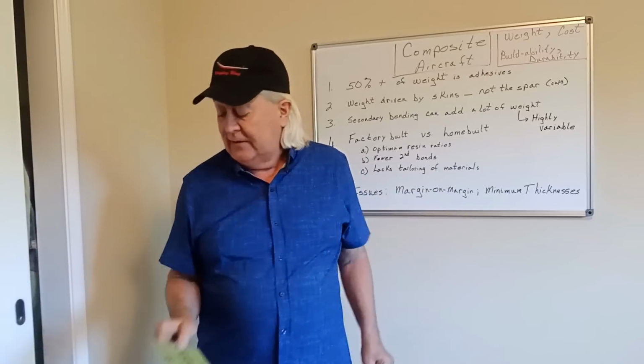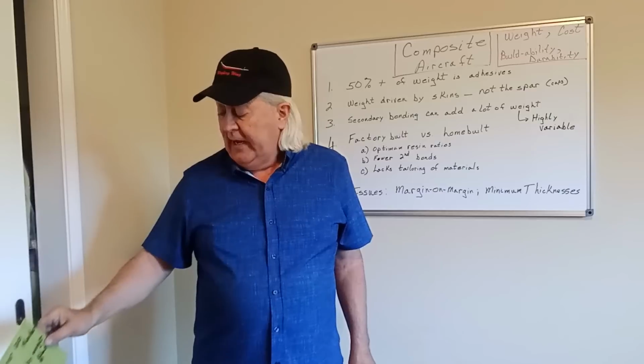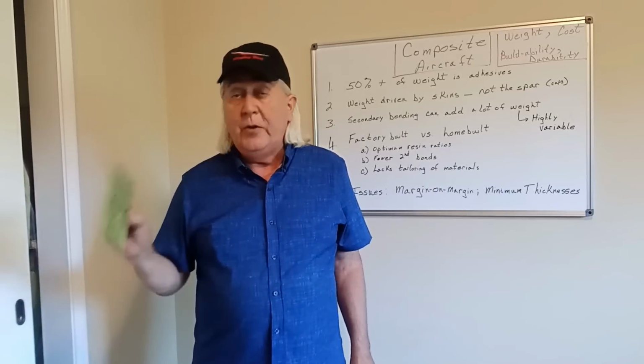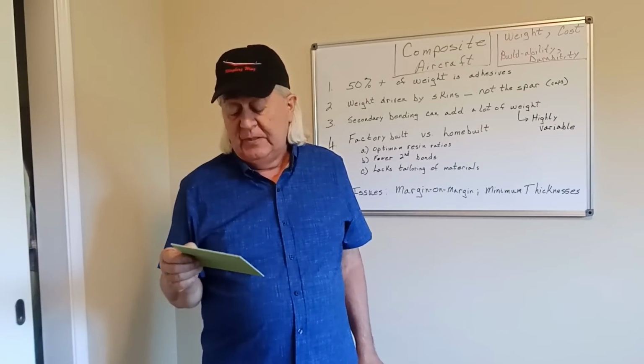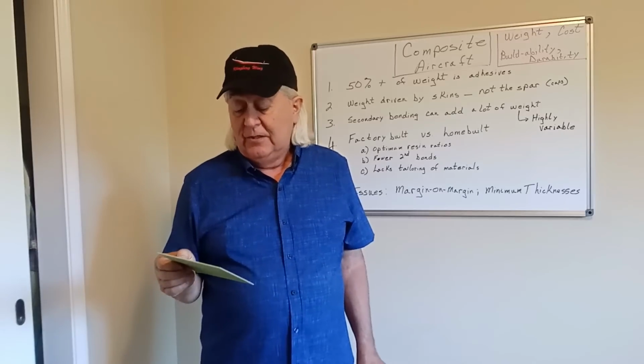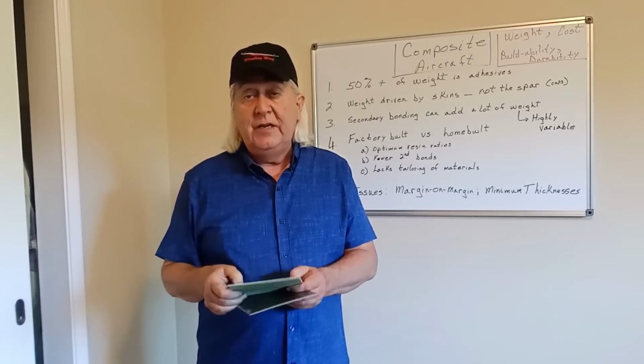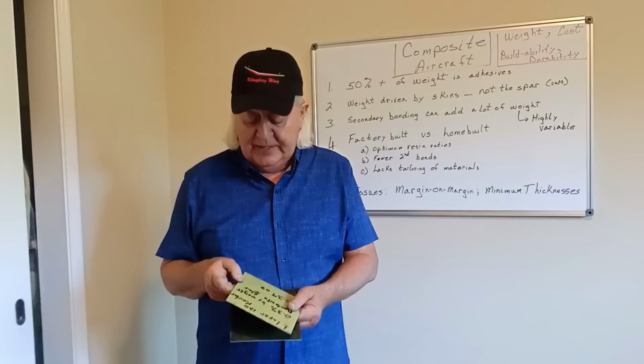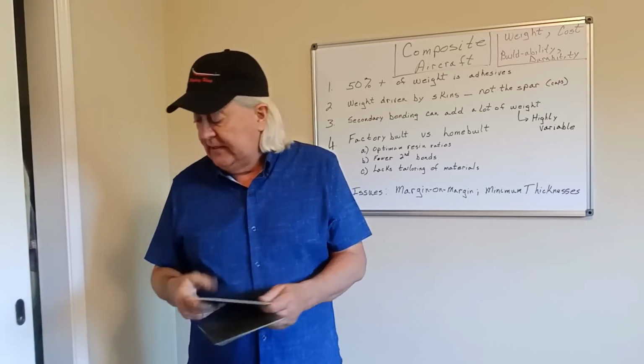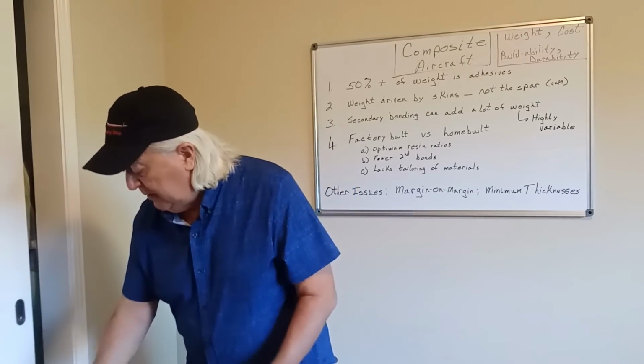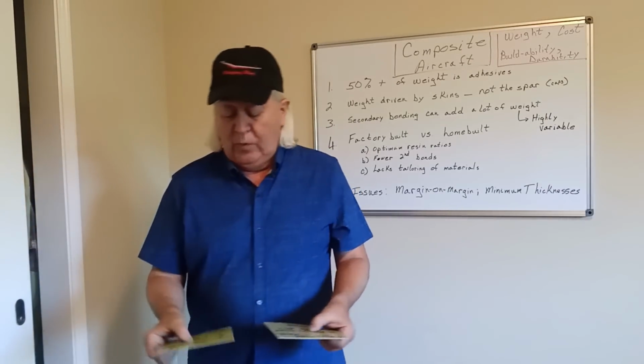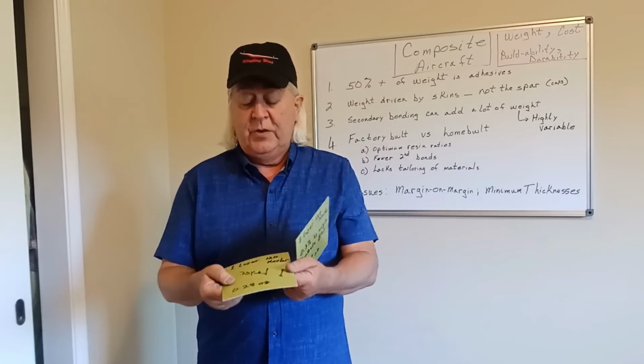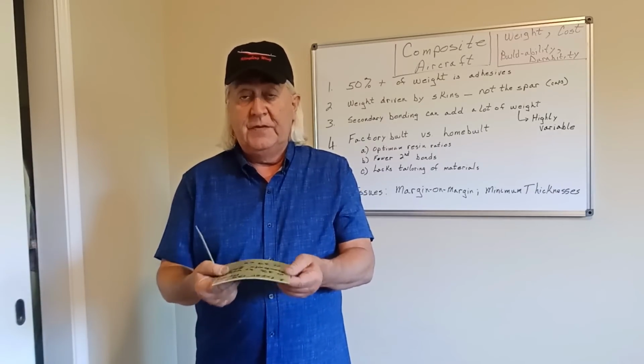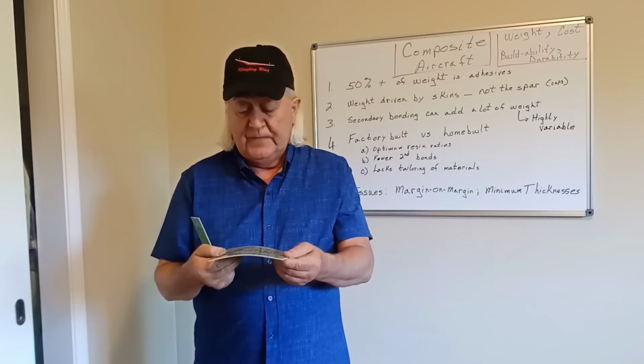This weighs 0.39 ounces, so we were at 0.28, and for an additional 0.11 ounce, in other words, essentially 1/10 of an ounce, you get the added durability from the ply and bending stiffness. And I'll tell you, I put down this other one. If I actually had weights here and so forth, I could show you, but this one here is more flexible than this one. This one is definitely stiffer.